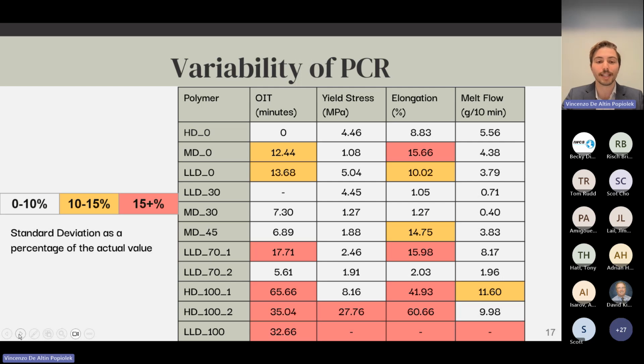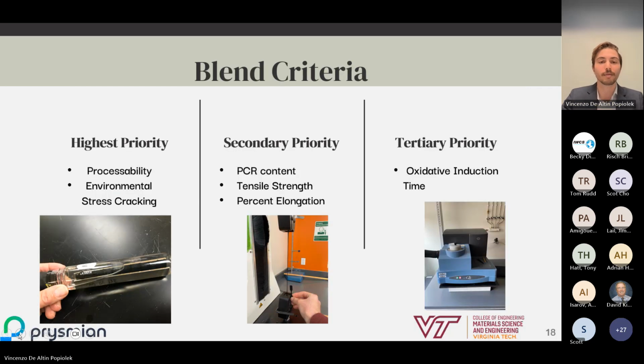While as we go to 70 to 100% PCR, we see those ranges increase up to 65% for some categories, which is much harder to use and borderline unusable. And that is something that we had to consider when blending. But we did hope that by blending with lower variation polymers, we would be able to decrease that variability in our final blend. From this, we were able to develop our blend criteria.